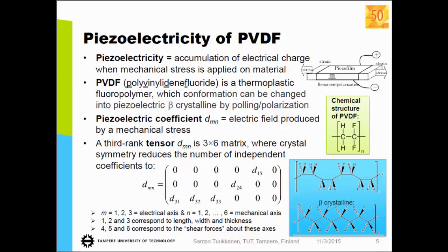And there is the piezoelectric coefficient tensor matrix, which describes the electric field produced by a mechanical stress applied in different directions. So you have the subindex M defining the electrical axis, and another index N defining the mechanical axis, and these indexes 4, 5, 6 correspond to shear forces. And then by calculating the symmetry of the structure, you can get these non-zero components for the matrix.